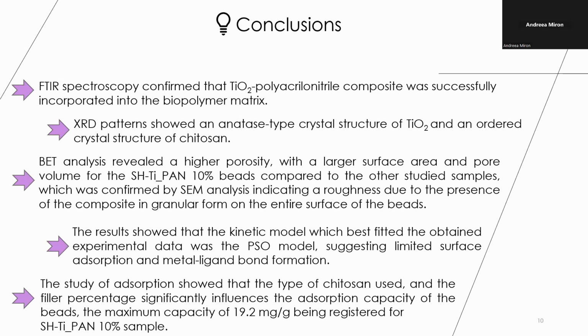X-ray patterns show an anatase type crystal structure of titanium dioxide and the ordered crystal structure of chitosan. BET analysis reveals a higher porosity with a large surface area and pore volume for the sample with SHT pan 10%.